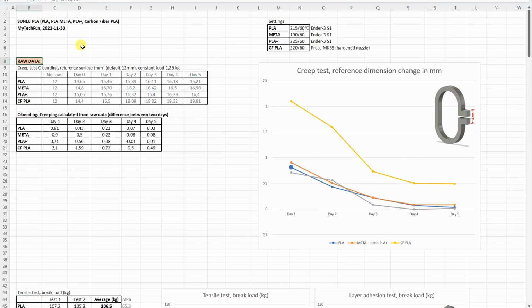And now let's analyze the data. I'm starting with the creep test. These numbers are directly measured values between two reference surfaces. But what we need is the difference between 2 days. That's why I prepared this table, and this can be visible on this graph. Here we can see these are very similar. After the third day, these are very minimal deformations. Only the carbon fiber PLA had a little bit more creeping even on the 5th day.